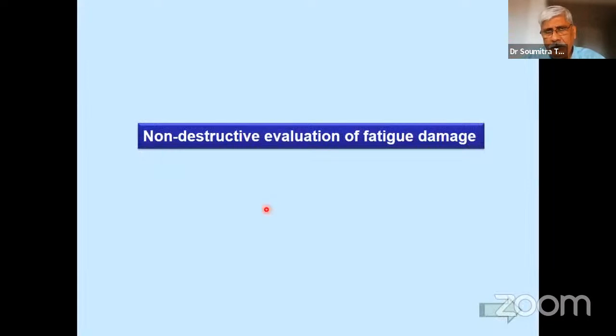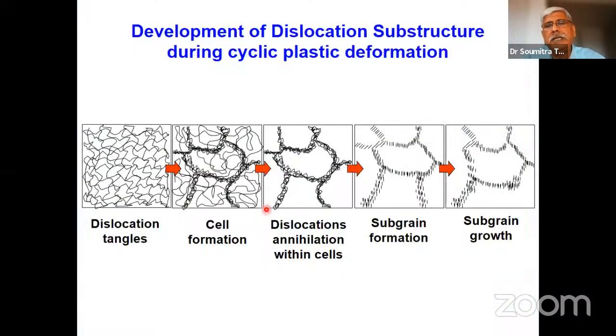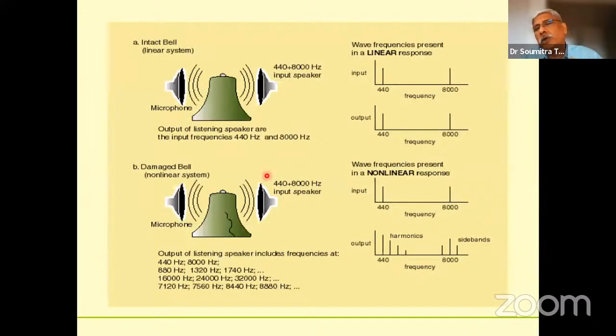So let me just present a few of the background R&D that we're doing. For example, to non-destructively evaluate fatigue damage. How do you do it? And this is all with non-linear ultrasonic. See, as I said, when there is fatigue damage, essentially what happens is the dislocation configuration in a material changes. So it goes into a cell type formation, some amount of dislocation annihilation, subgrain formation, and then subgrain growth. And after that, a micro crack is initiated and the crack grows. So if you can quantify damage in these stages, you can say if the fatigue damage is sufficient for us to live with. And that is what we have been doing using nonlinear ultrasonic.